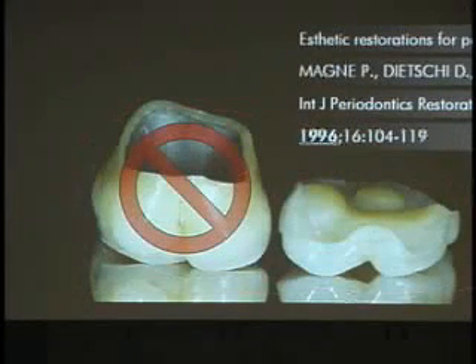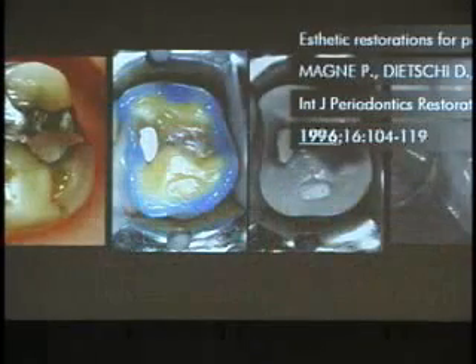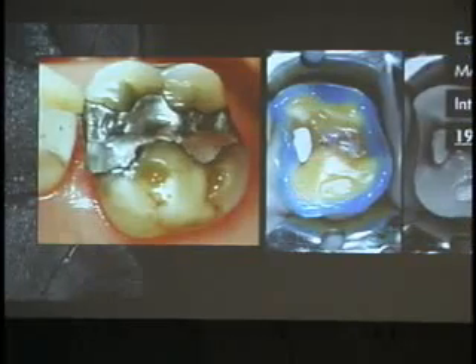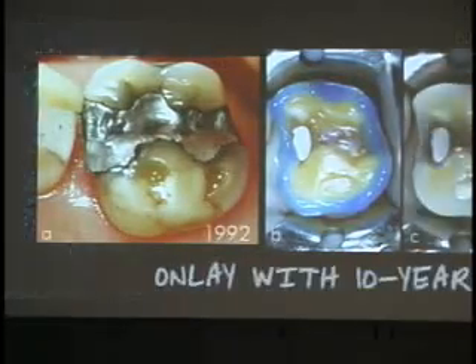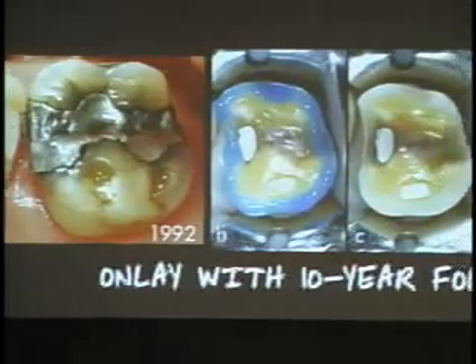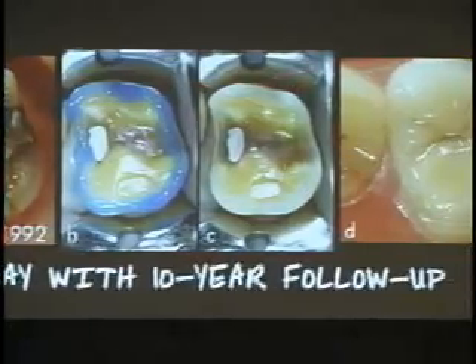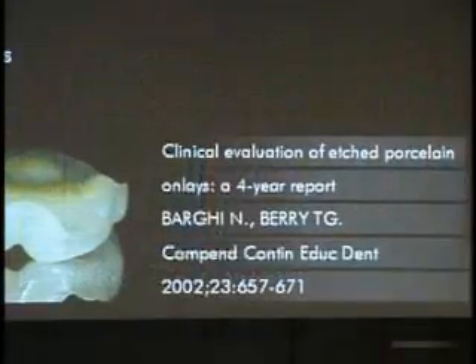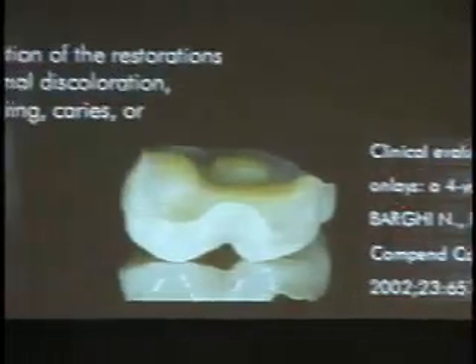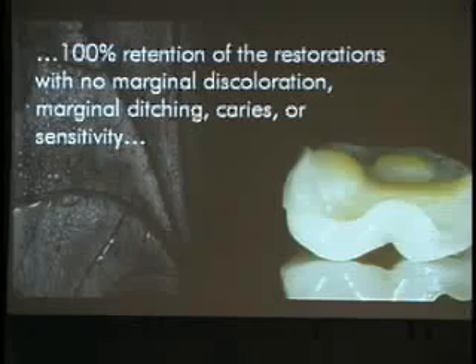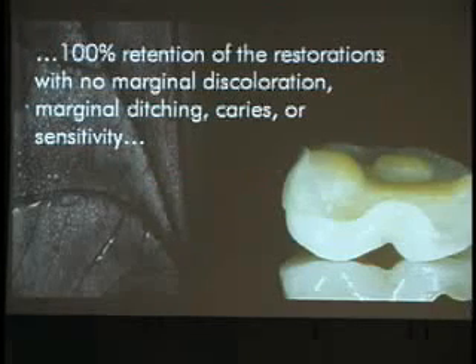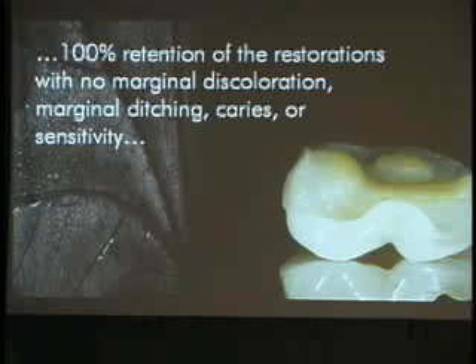So you see basically the gain of intact substance preservation given by adhesion, if you compare the PFM or any type of cemented crown versus the overlay preparation. That's my oldest case of this overlay. And this one, as you can see, was with a copalite and bonding only to marginal enamel. We had published that case, and now we have 10 years of follow-up. That's in 2002, the same overlay that I placed in 1992. There is no bonding to the underlying dentin. An interesting clinical study by Barghi and Berry, a 4-year report with these onlays, showed 100% retention, no marginal discoloration, no caries, no sensitivities. It's a very safe restoration, to say so.